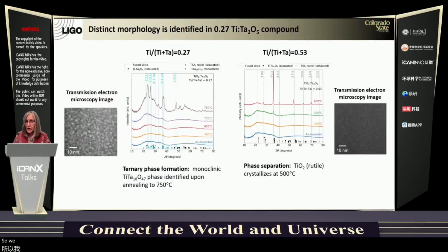So we have conducted extensive studies on mixtures, and in particular, the one that is used in the present LIGO coatings. And to this picture of reorganization, what our studies have added is that for a specific content in the titania doped tantala of about 27%, when the alloy is annealed, there is a reorganization that takes place that is reflected at the crystallization stage by the formation of a ternary phase whenever the concentration is 27%, or instead, when the concentration is higher, we see that only titania crystallizes in rutile.